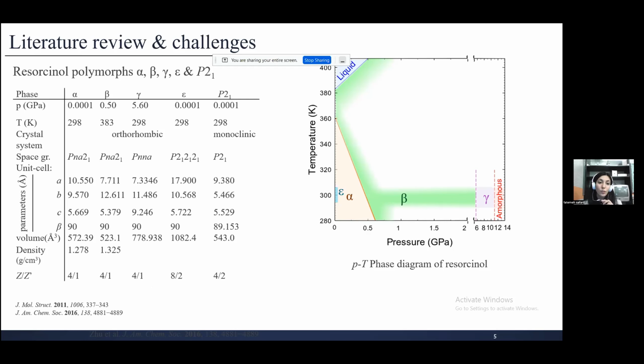And what they did, actually, they are not high-pressure researchers. They tried to mix resorcinol with tartaric acid, and after melting, they got a powder. So they did powder diffraction, and from the powder diffraction data, dynamic simulation and some computational work, they predicted that the structure in this powder could be epsilon. And in the same paper and report, they also predicted that it is possible for resorcinol to have the space group P21. So according to the literature, I drew the phase diagram of resorcinol.